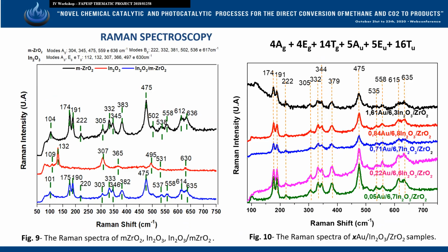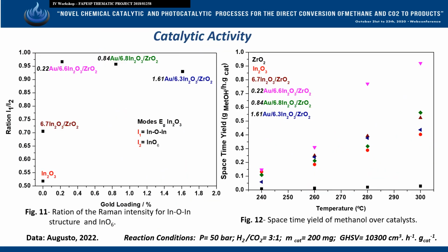The Raman spectra of the samples indicate preservation of vibrational modes assigned to monoclinic zirconia at lower intensities. The indium load in the sample is less than 7% and justifies the relationship. The intensity of the indium-oxygen mode increases with the presence of zirconium, suggesting that more oxygen vacancies are generated.